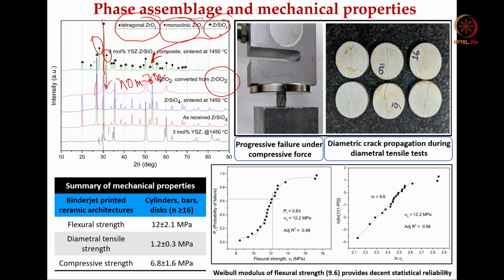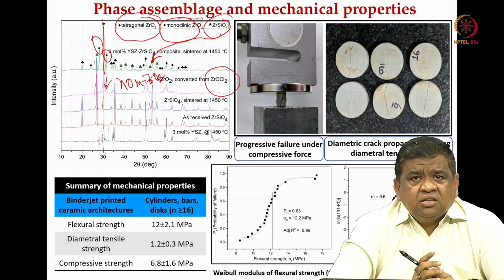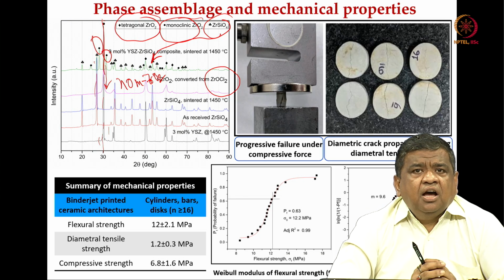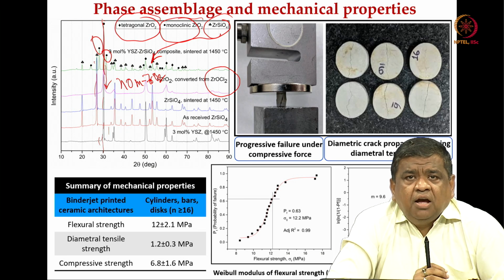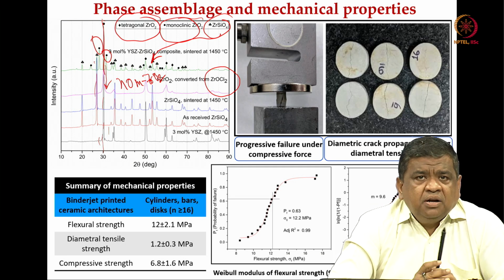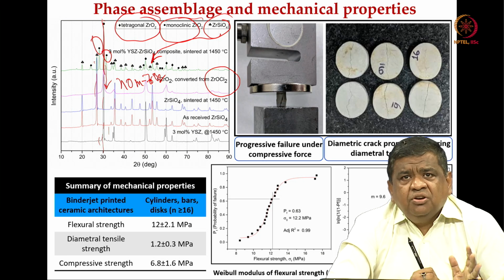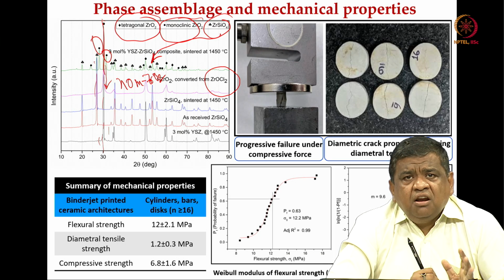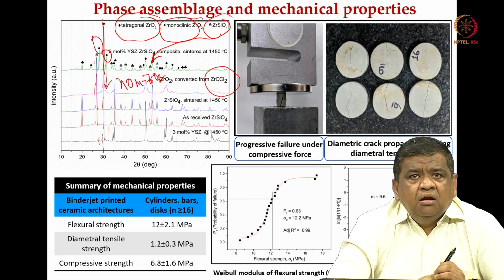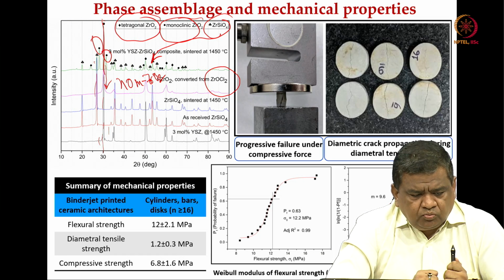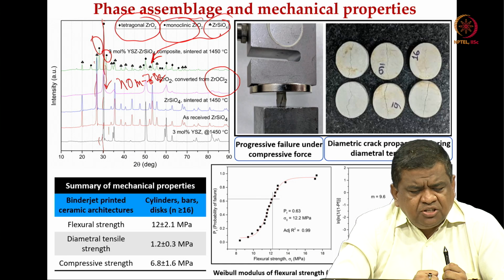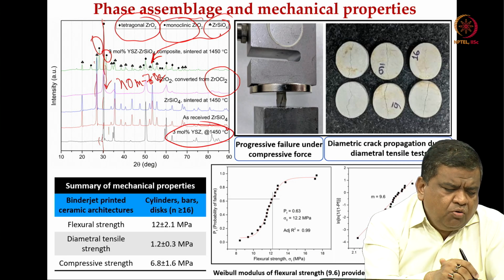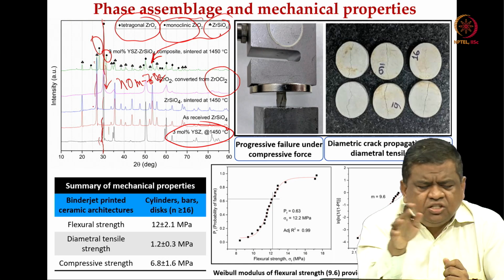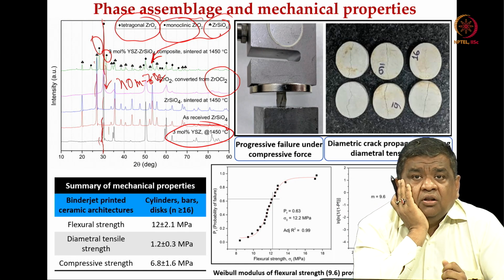So, in order to have a good zirconia product, one should always remember that you must have as little monoclinic zirconia as possible and as much tetragonal zirconia as possible, particularly in 2 to 3 mole percent yttria stabilized zirconia products. Whenever we are handling tetragonal zirconia polycrystals, our aim is to retain 100% tetragonal zirconia in the final as-processed samples. As you can see, 3 mole percent yttria stabilized zirconia at 1450 degrees Celsius is pure tetragonal phase, it is a strong phase, and there is no deviation or peak shifting.